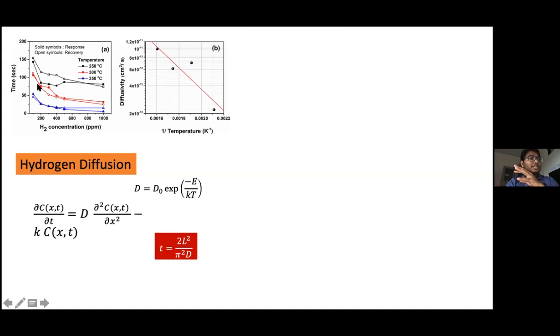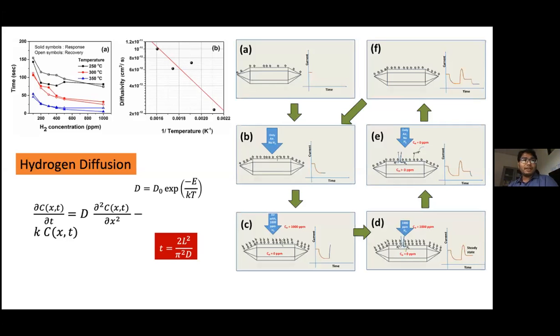So what we were seeing, you can see from this graph, beyond a concentration of 200 ppm, the response time was actually independent of concentration. Anything lesser than that, at 200 degrees, it was fairly changing, but after that it didn't matter how much gas concentration was there outside. So what understanding we developed was as follows. You have this ZnO microcrystal, and you have oxygen which is surface adsorbed, which leads to a surface state. That surface state forms some kind of a depletion, and I have multiple such needles which are joined together, and the current takes its own path.